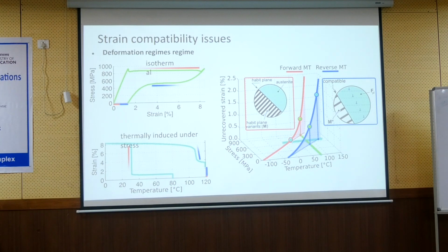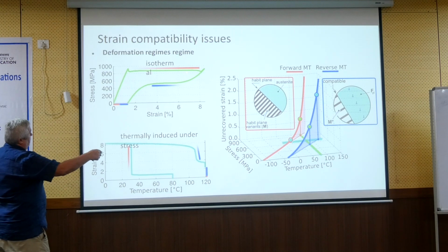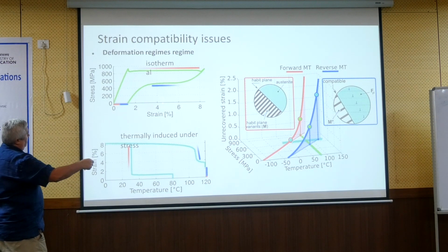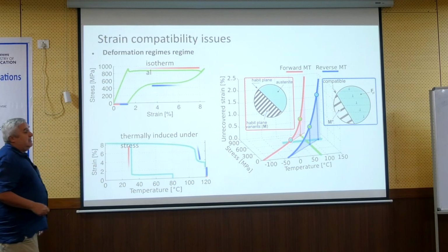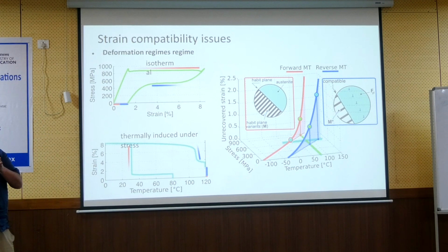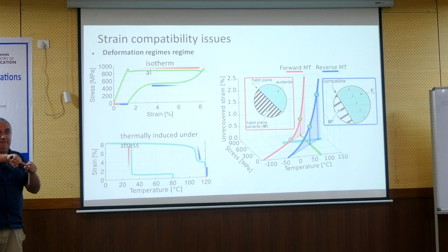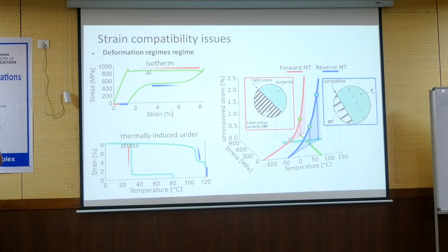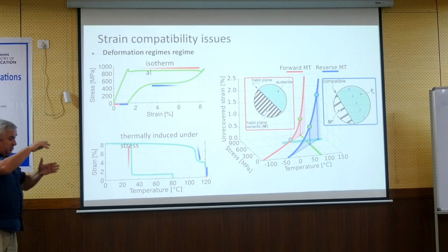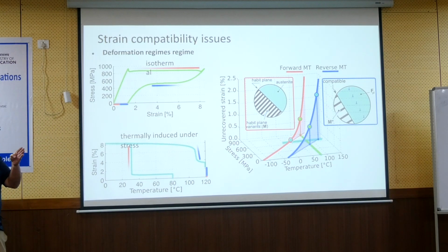So this is for a single cycle. What about repeated cycles? Well, repeated cycling, this is the problem. You would come here, and it will come up here, and like that, it's accumulating, but slowly saturating, but accumulating, and the saturation curve would look like this. So here you have thousands of cycles with some constant slope. There will still be some small increment. Of course, if the temperatures are low or stresses are low, it would look more flat, you know? But it will still be there.